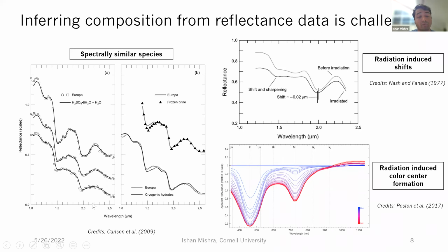So 1.5 and 2 microns are the two big water ice absorption bands. And when you have hydrates, when you have salts and water molecules attached to the salts as water of hydration, the primary effect in the near infrared is to distort the water ice band. And because many of them can distort the water bands in a similar way.